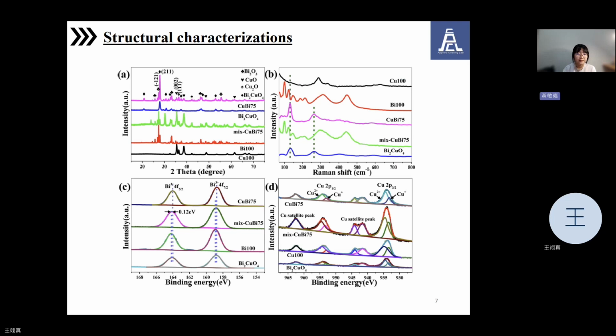And picture A is the XRD patterns. As the diffraction peaks show, Cu100 and Bi100 are pure controls. The CuBi75 and mixed CuBi75 both contain some mixed phases. Picture B is the Raman spectra. The CuBi75 and mixed CuBi75 show the peaks from both Bi2CuO4 and other oxides, indicating the successful combination of copper and bismuth. Picture C is the XPS spectra of Bi.